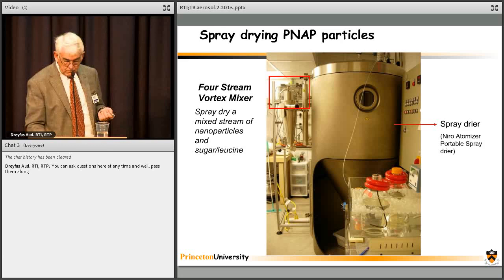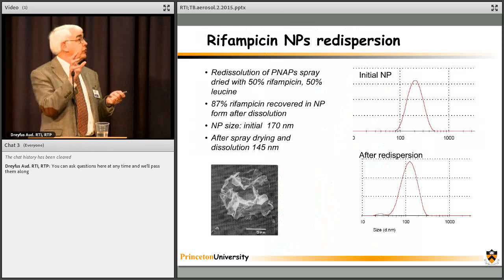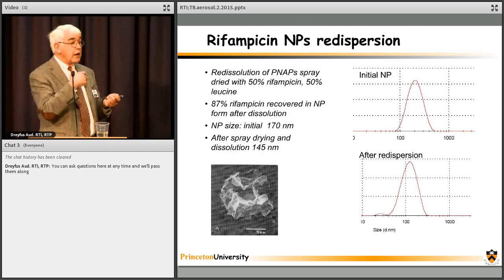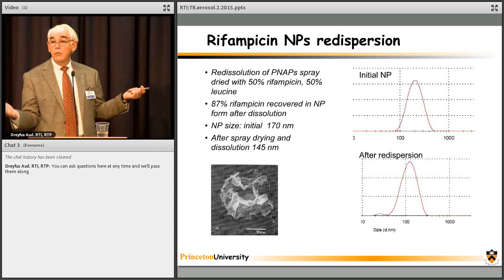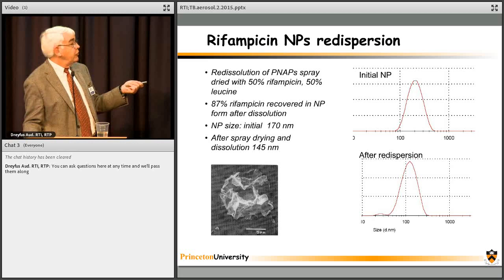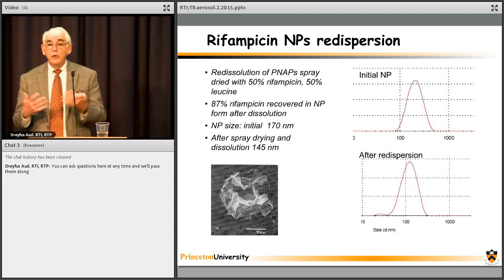Here, we actually made a set of these rifampicin particles separately and injected them in the spray dryer. We just wanted to see, when you dissolve the matrix, do they disperse back to the original nanoparticle form? So here are the original ones, 170 nanometers, put in this form right here. This is 50% nanoparticles, so we have really high loadings of nanoparticles here. You put it in water and it disperses back to these 145 nanometer particles. So you do not get aggregation during this drying process because the dense PEG layers on our surface keep the particles from aggregating.